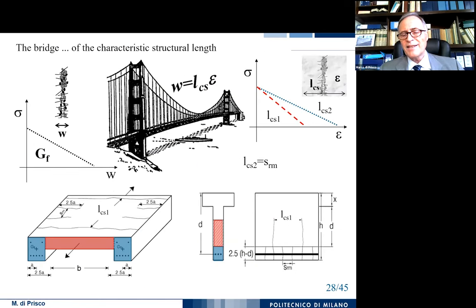The structural characteristic length can also be not homogeneous in the cross section. In that situation, you can have some red zone where the crack distance is huge. And so, starting from the same stress crack opening, you have a different slope in the post peak for a linear residual model. And you see the two zones where the crack distances are different. And for the same constitutive law identified, you have two different constitutive laws that can be used in the same cross section.